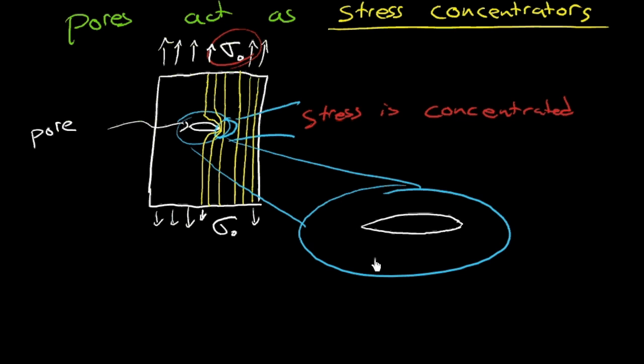And for a simple case of this particular crack, we can actually quantify that. So I'm going to draw that crack out again here. For this simple case of a crack, and I'm going to give it dimensions for you here. What's important about a crack? Well, how long the crack is, crack length. I'm going to call that A. Actually, correction. We're not going to call it A. It's a little funny. I bet I should mention this here anyway. If I make a crack on the surface, it would just look like this. There's really one crack here, just that tip. And so what we do is we define this dimension here as A, the crack length. And so you can sort of think about this internal crack as having two ends on it, doesn't it? It's like that sharp end there and that sharp end. So the crack length of this internal crack, we'd call 2 times A, because you've got over here and over here. You've got A. You've got two cracks back to back, if you will. So that's the way the math works, so that's what we do.